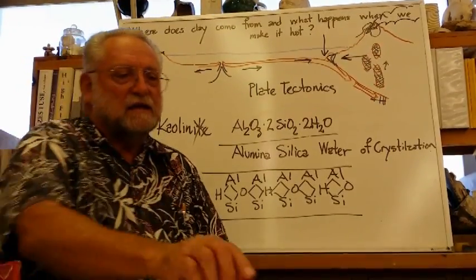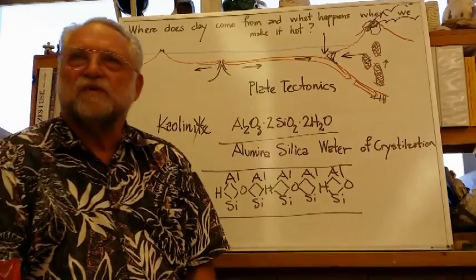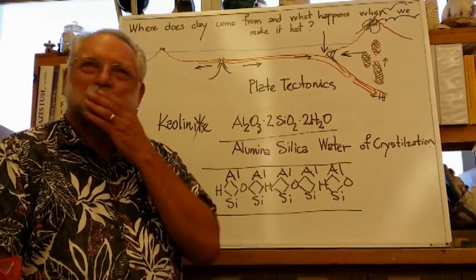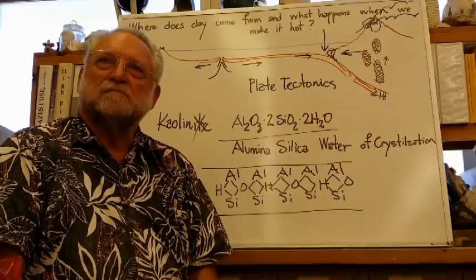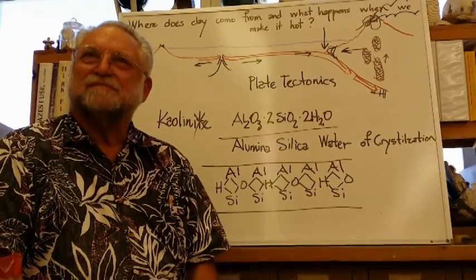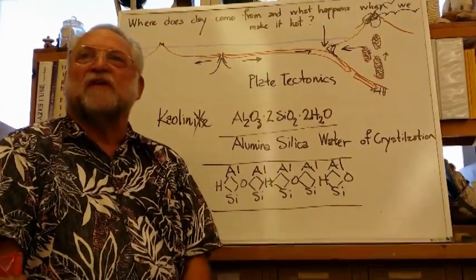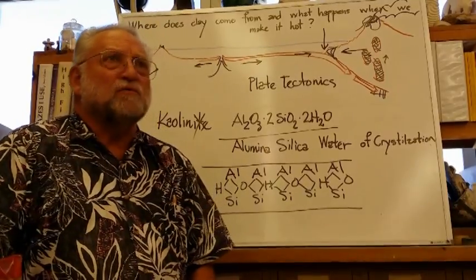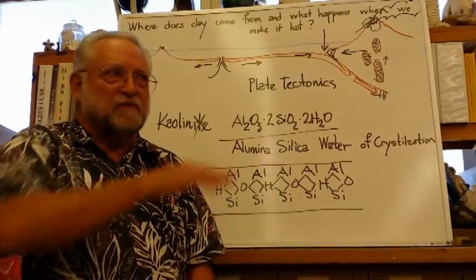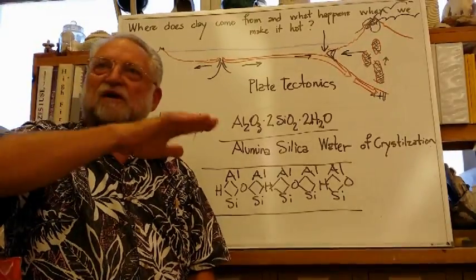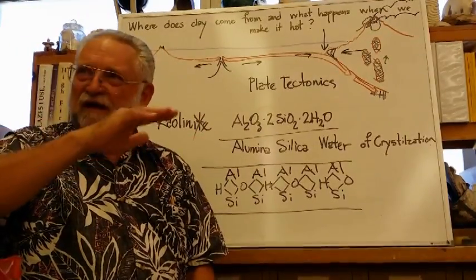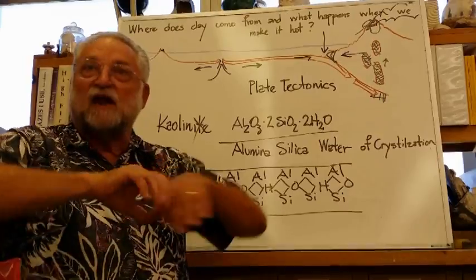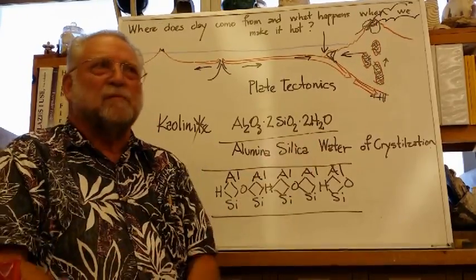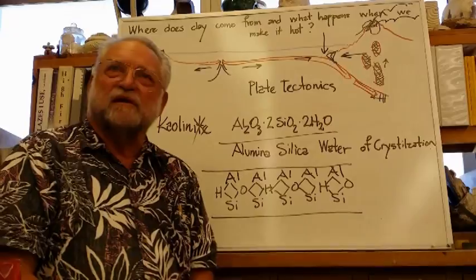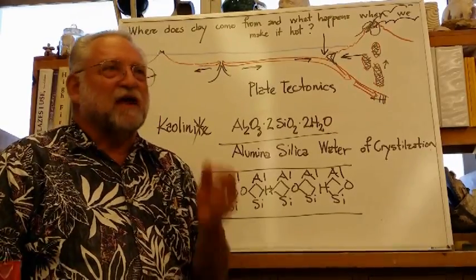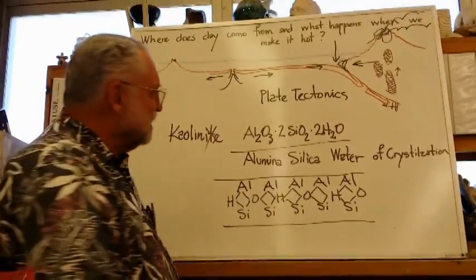causes the sag. Yeah, I guess some of those really old churches, cathedrals that had the glass windows and stuff, they found that the glass is thicker at the bottom of the pieces. Yeah. Because of course, they're hundreds of years old. The manufacture of glass was not done so sophisticated as we do today, where they float the liquid glass on liquid hot metal. Gravity gives them a flat. When they hand rolled those sheets of glass, probably a little bit less likely to be uniform in thickness. But independent of that, glass is still fluid.